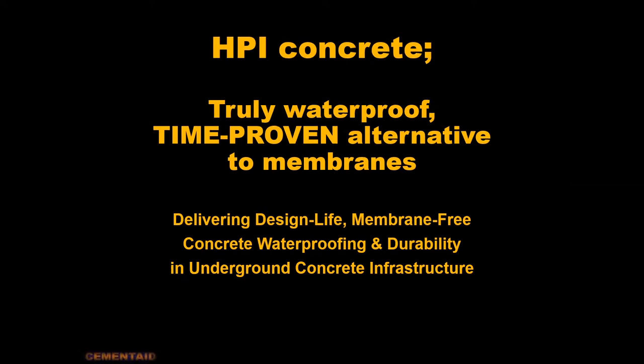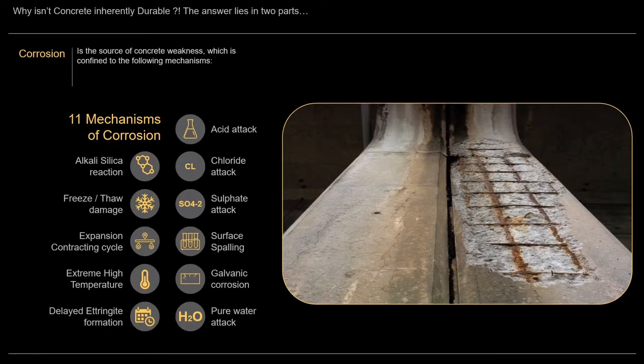And what we're going to present here is HPI concrete. It's an alternative for membranes, delivering high design life, membrane-free concrete waterproofing durability in underground concrete structures. If we look at the potential for corrosion, they all have one common denominator. We'll go through, there are 11 separate mechanisms that we've identified, and we'll go through them fairly quickly. But alkali silica reaction, you require obviously potentially a reactive aggregate in a highly alkaline cement situation. The catalyst for the reaction, however, is water.